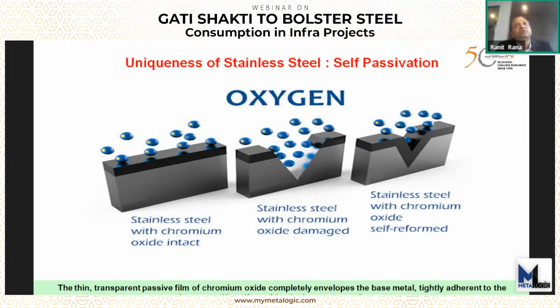So if we try to select a material which will be able to meet the three S's of smart transportation, as well as operate in a highly corrosive country like India, stainless steel comes to mind on a preferential basis. The reason being that there is a unique property of stainless steel, which stems from the fact that it is self-passivating in nature. So, unlike a coated steel or a painted steel, where, when we do the working with that steel, there is a propensity of the coating getting peeled off at some micropores, and from there the corrosion initiating. And once the corrosion initiates, it's very, very difficult to stop that.